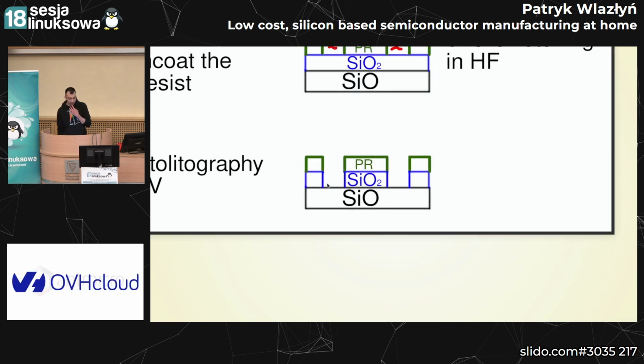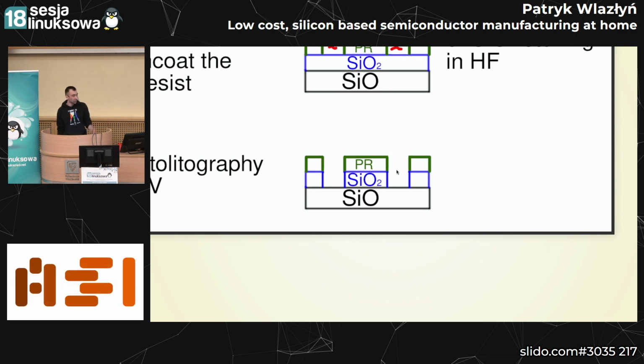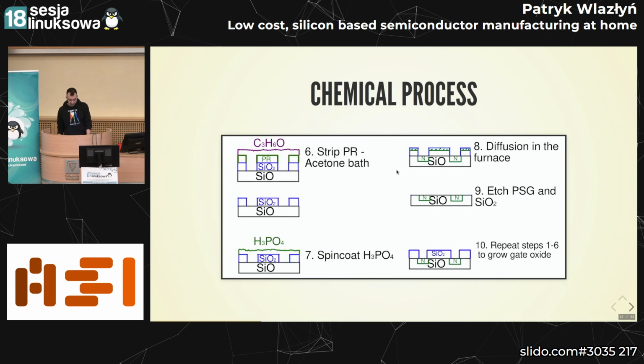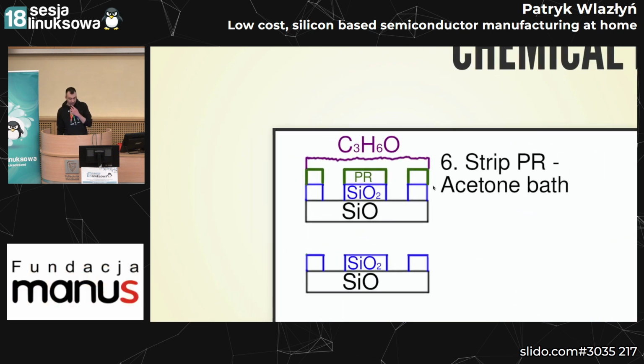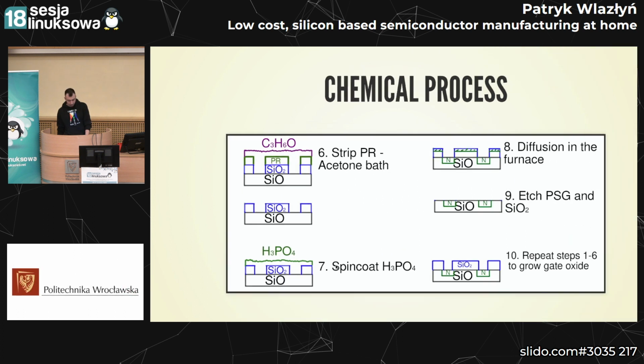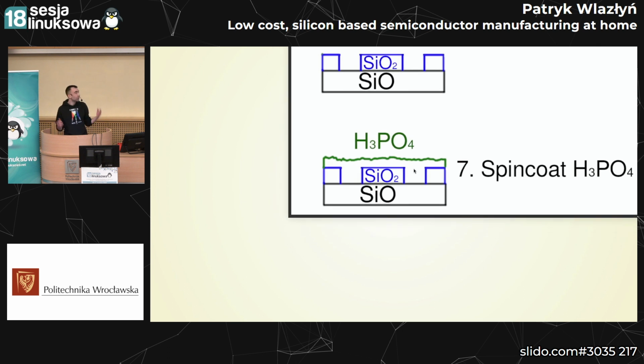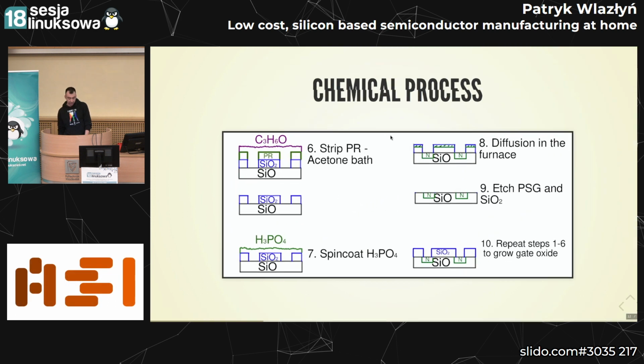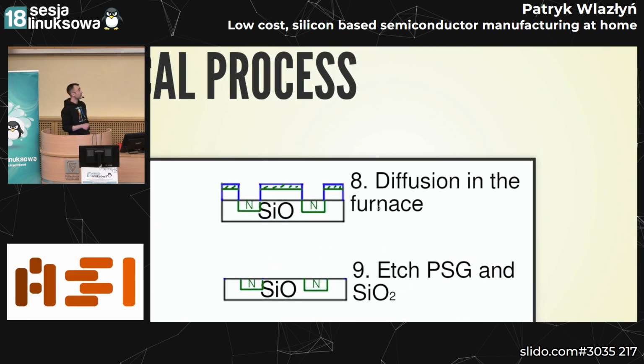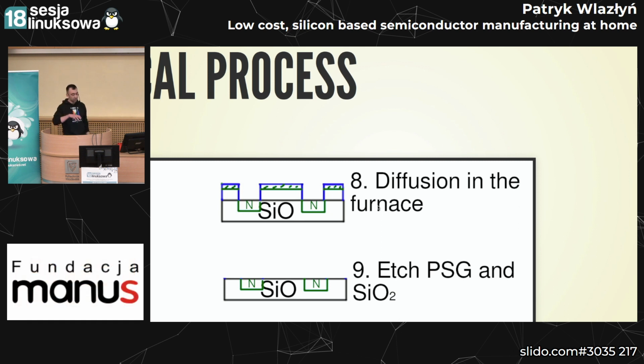So we have a silicon wafer that had a silicon dioxide on top, and there was a photoresist that was washed off by shining UV light on it. And when we have something like this, then in this example, we have an acetone bath to clear out the photoresist. And later we can use, for example, phosphoric acid, something with a phosphor in it. Phosphoric acid is actually easy to use because it's a liquid, and we can again very easily put it on a whole wafer. And when we do it like this, we can again use a high temperature in the furnace to drive the atoms of the phosphor into the silicon by simply applying the heat.